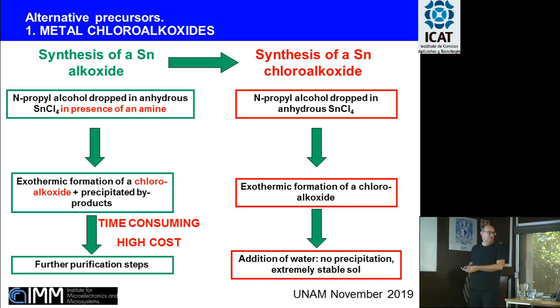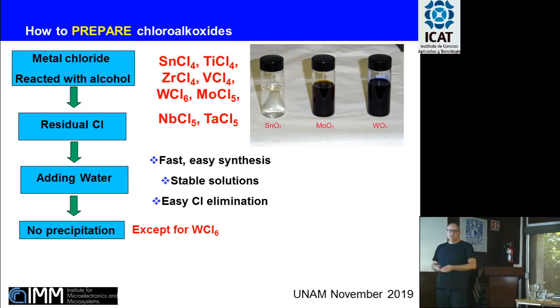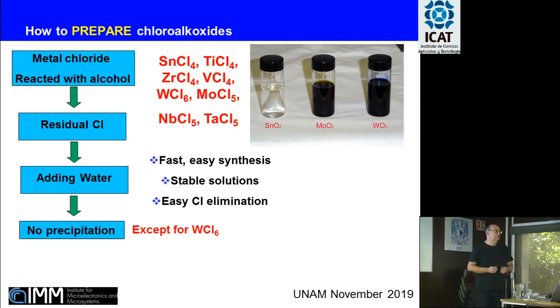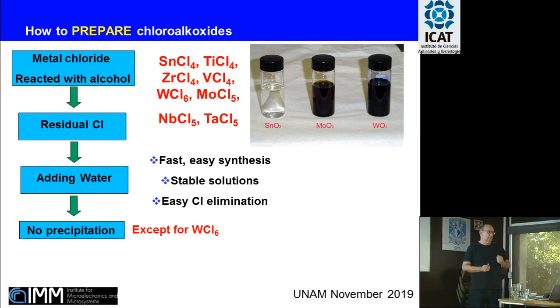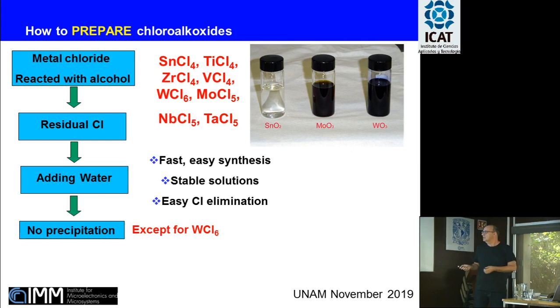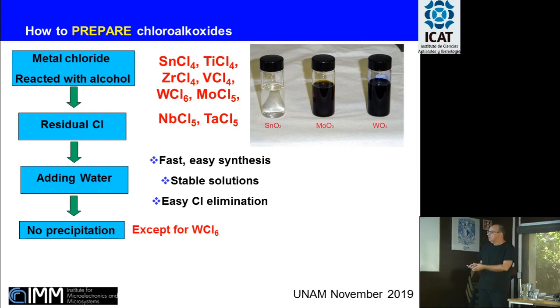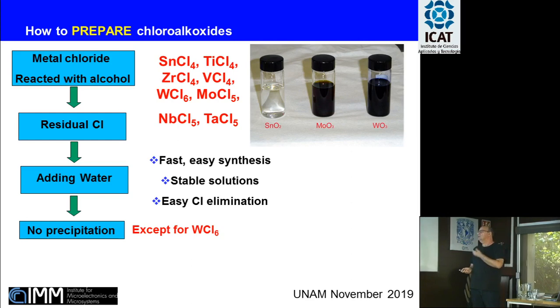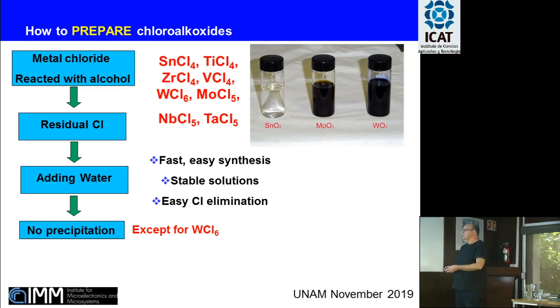And now let's see if really some thin films could be achieved with these chemicals. If you remember from a few slides ago, one of the possible advantages of using chemical processing is that you can use the process like a coffee machine, I would say. And this was the case. We had exactly the same procedure. Some metal chloride reacted with alcohol, some residual chlorine which stabilizes the precursor. We add some water, we don't have any precipitation. And in this way, we could prepare chloroalkoxides from tin, titanium, zirconium, vanadium, molybdenum, and so on. There are many possible elements which can be processed in this way. The synthesis is fast and easy. You don't even need to use a glove box. You have a stable solution, and easy chlorine elimination after heat treatment, or in some cases, after the spin coating of the film.